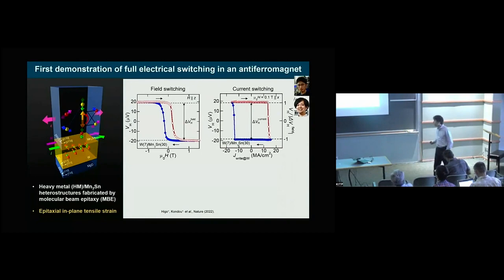Thank you very much. Yeah, that's a very important point. So in order to apply a torque, what is important here is that the spin polarized current has to go into this magnetic Kagome plane with polarization direction perpendicular to it. So the spin is somehow polarized along the perpendicular direction to the Kagome plane. But this is an easy-plane material, so the out-of-plane component is very, very tiny, and that actually provides a constructive torque. But the octupolar moment switches within the plane, not coming out of the plane. Yes.